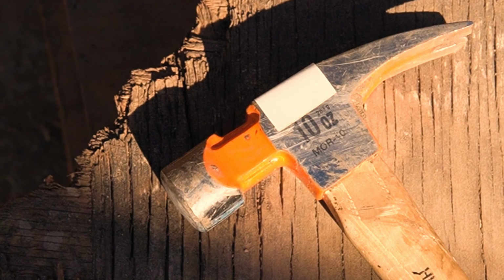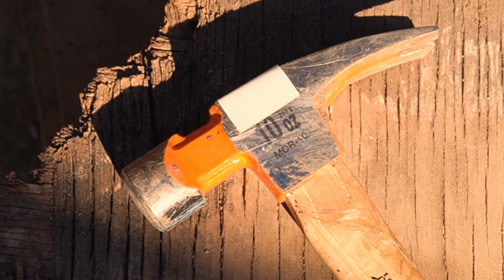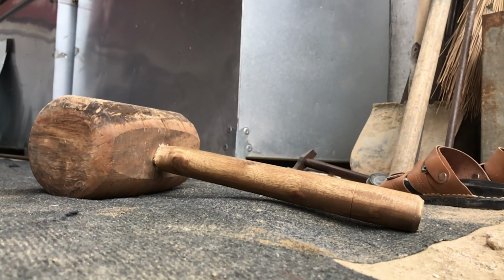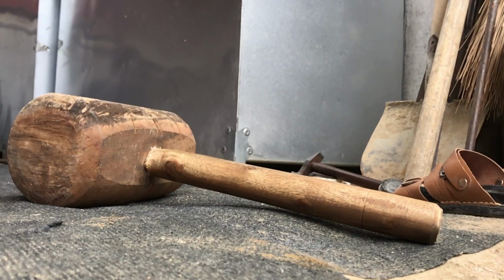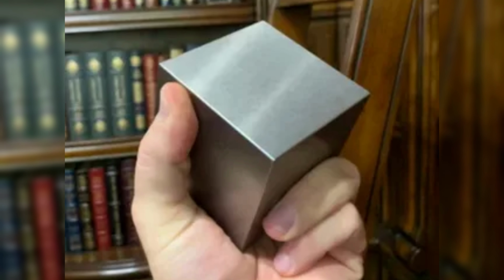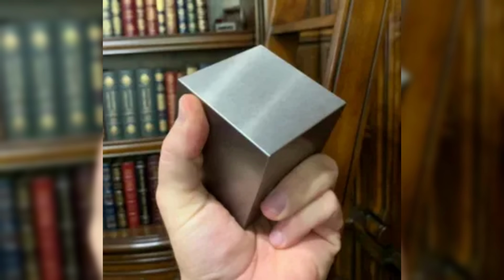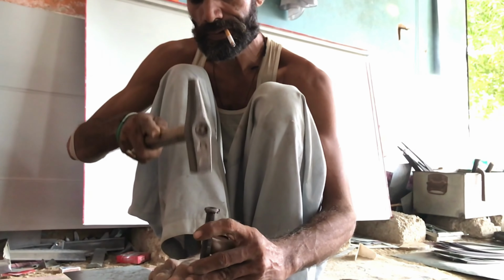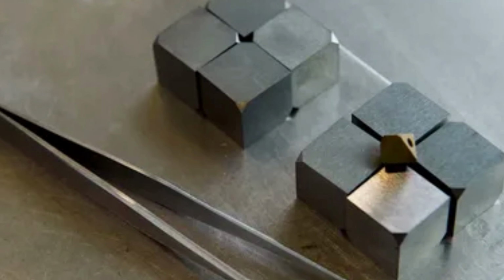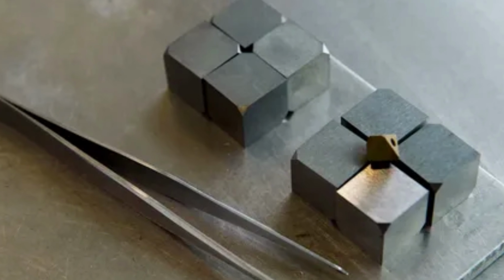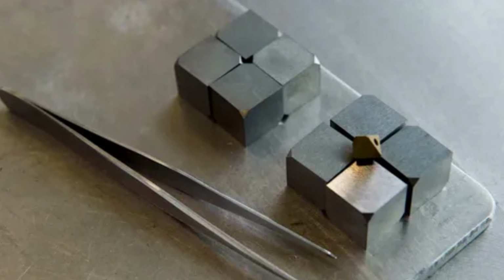The hammer strikes true, but this time the head of the hammer flattens a little against the cube. A crack appears on the hammer face. The cube? It has one small flat spot from the force, but mostly it looks the same. More hits follow. Each one makes the anvil shake. The cube gets hotter, but it fights back. Tiny cracks form on its edges now, not from bending, but from the shock of the blows.